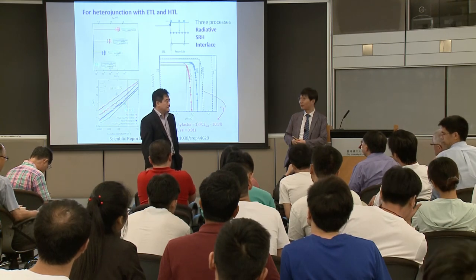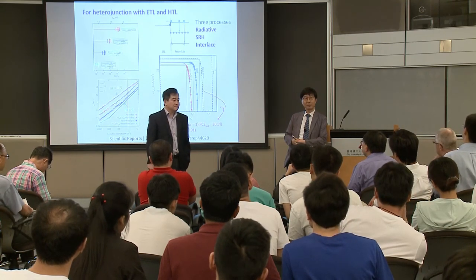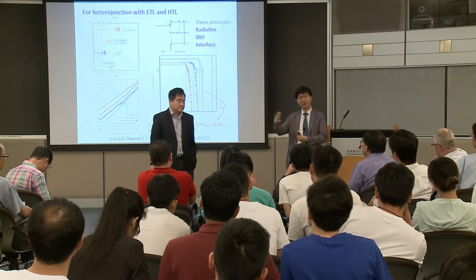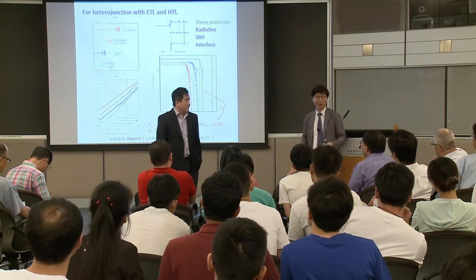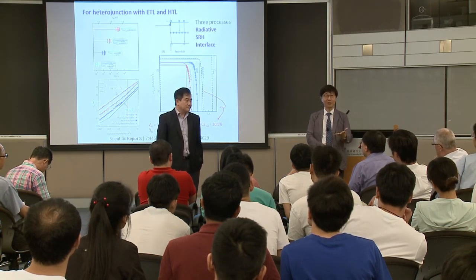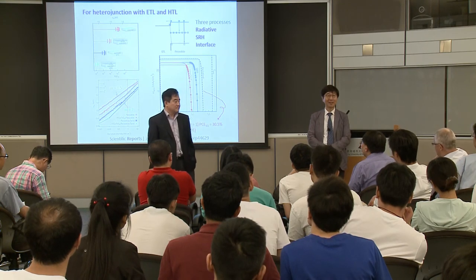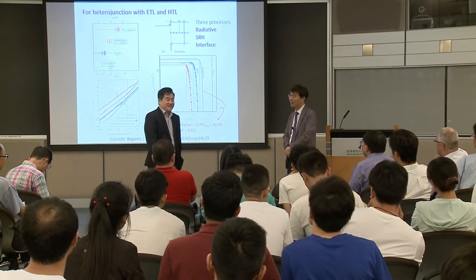So the organic A cation plays a very important role, not only in the photovoltaic performance, but also in the thermal stability. So do not change the inorganic cation. This organic cation is magic, actually.